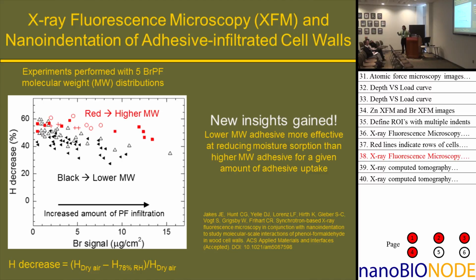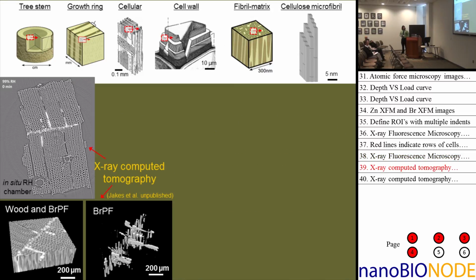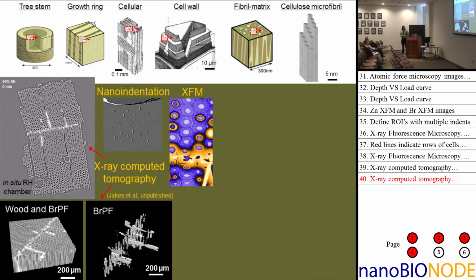So this is a new insight, but just nanoindentation and cell wall characterization on their own don't provide the whole answer. This is really part of a multi-scale approach that we're taking to map out adhesive infiltration at multiple length scales. At the APS we also built a humidity chamber, and we're doing X-ray computed tomography experiments of wood adhesive bondlines. The cool thing about using this brominated phenol is that there's enough of a difference in attenuation that you can use software to separate out the adhesive, so you really see the adhesive structure inside the cell wall. Then of course we've also got our nanoindentation and fluorescence microscopy.